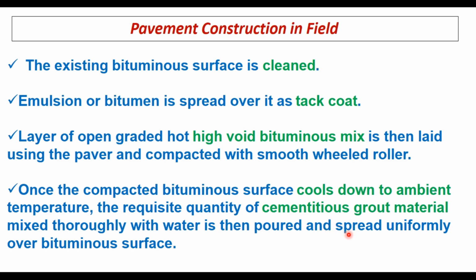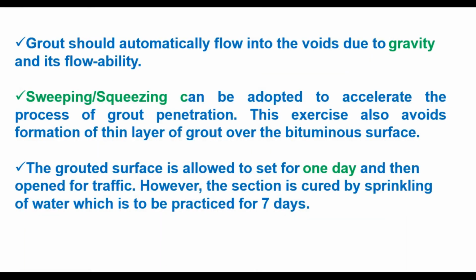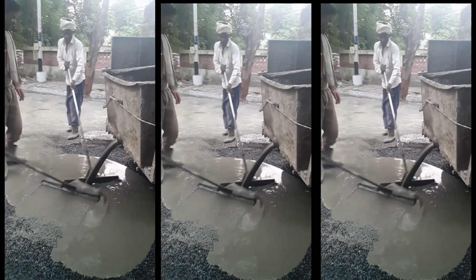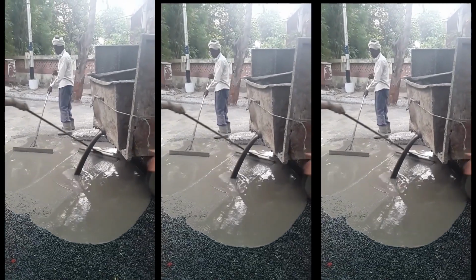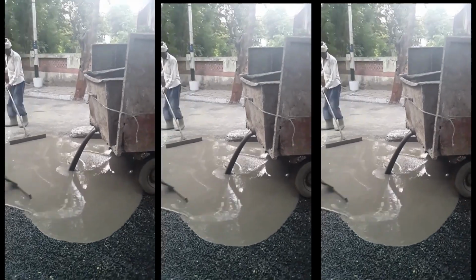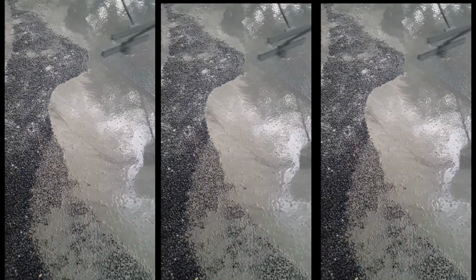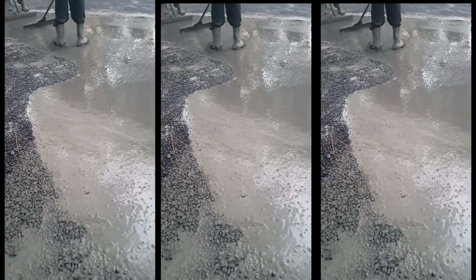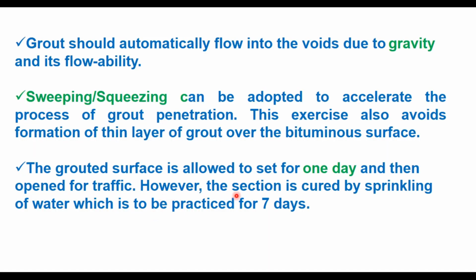and spread uniformly over the bituminous surface. The grout should automatically flow into the voids due to gravity and its flowability. But sweeping and squeezing can also be adopted to accelerate the process of grout penetration. This exercise also avoids formation of a thin layer of grout over the bituminous surface. The grouted surface is allowed to set for 1 day and then opened to traffic. However, the section is cured by sprinkling of water, which is to be practiced for 7 days.